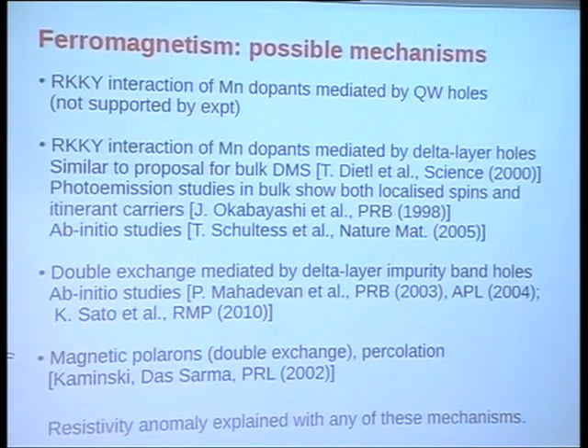So finally there is yet another proposal which is essentially double exchange, but at very weak ionization of the Mn dopants. This is a polaron picture of Das Sarma and Kaminski. So the idea is that whenever you have holes at the polarized Mn atoms, they overlap with a lot of Mn atoms here, and because of double exchange they all get polarized in some way. Then you have another hole here which has maybe a weak overlap with this fellow or no overlap at all, say at high temperatures, and this may be polarized in some different direction. And when the temperature is low enough, these start overlapping, and at a certain temperature they percolate, and that's the onset of ferromagnetism on a long length scale. So this is the polaron picture.